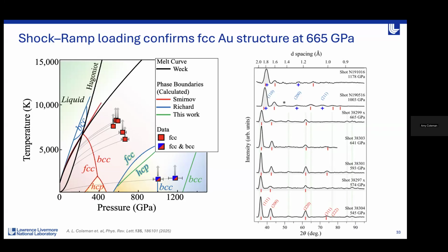So there wasn't actually a measured transition to BCC — it was just a very difficult data set to analyze due to overlapping peaks. Advances in our diffraction analysis techniques let us see it was actually FCC. What that means for this gold paper is that the observation of FCC up in the terapascal regime is the first off-Hugoniot FCC measurement made using these techniques, which is very exciting.